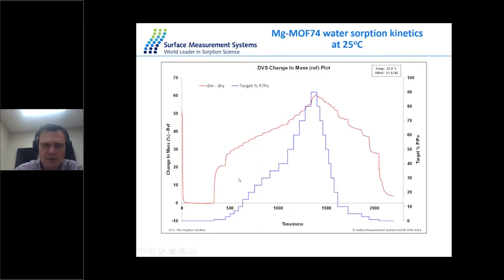Now here we're looking at the Mof 74 water absorption kinetics. The solid red line is the mass, and the solid blue line is the partial pressure of water in the vacuum. Throughout my presentation, the red line will always be the mass, and the blue line will always be the pressure. As you can see, we're getting good kinetics, nice mass equilibrium, and many pressure steps. As you can see, the stages are different. This suggests that the experiment was done in the dm/dt mode with the mass equilibrium criteria, because you can do the same experiment in time mode, so you know exactly when the experiment finishes, but there is no guarantee you reach the equilibrium.